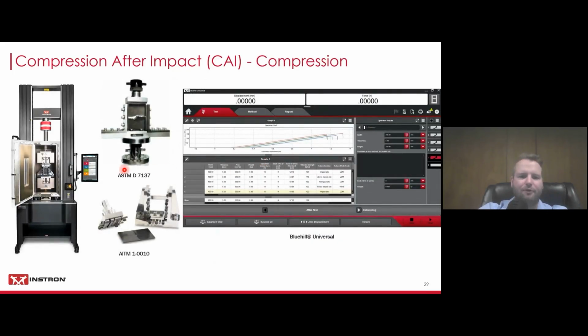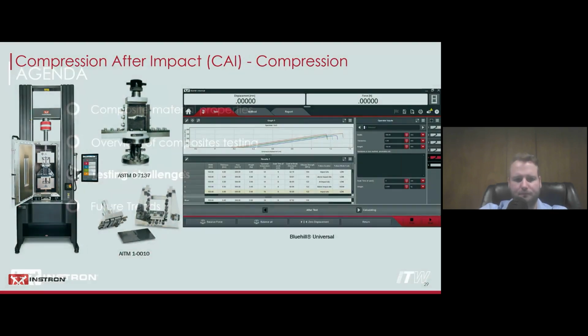And then you go a step further and you take that already impacted specimen and you put it in a test fixture, depending on the testing standard that you're following. Again, there's ASTM standards, there's Airbus and Boeing standards, as they need to simulate this. And then you compress that fixture with the already impacted test plate, and then it gives you the residual strength of your composite after it has been impacted. This is typically done to simulate something like a tool being dropped on an airplane wing or something, or maybe a bird that unfortunately hits the plane. So you need to make sure that if an event like that were to happen, your material still has enough strength left to carry all the loads and not fail in operation.